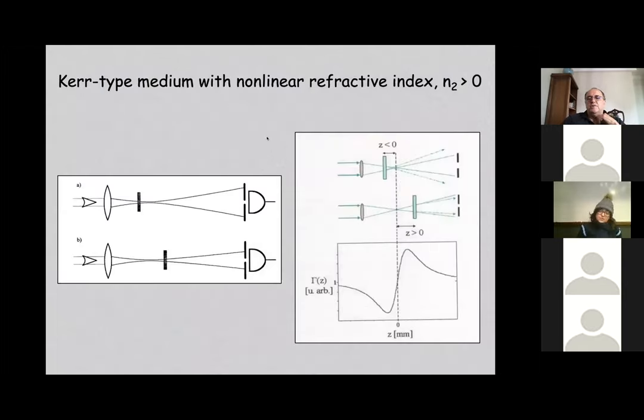Well, to measure this nonlinear optical susceptibility, we use a technique that I will show you in the next slide, which is the Z-scan technique. It is a Kerr effect. Basically we have a laser beam with a normal lens. We have a focal point at that position. After the beam opens, you put an iris in front of the detector.